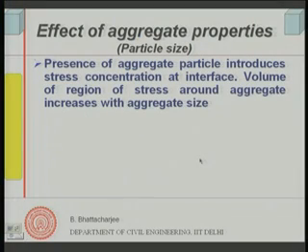So, let us see what the explanation for this one is. First of all, the presence of coarse aggregate particles introduces stress concentration, because it is a non-uniformity in the structure. It is a non-uniformity in the structure of the matrix, and then you have some inclusion inside this. We said paste acts as a matrix, and the coarse aggregate particles themselves are dispersed within that. So, they act as inclusions. For the stress flow, that would introduce a kind of discontinuity and stress concentration at the boundary of the